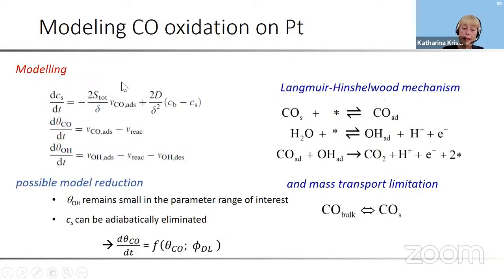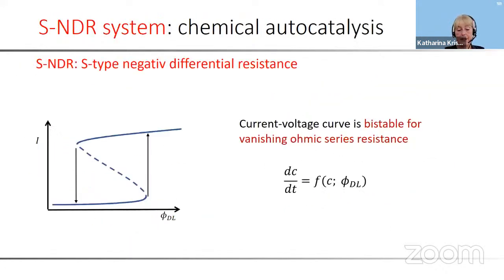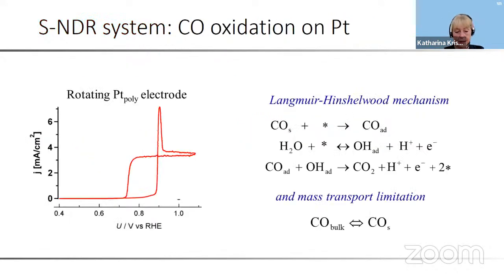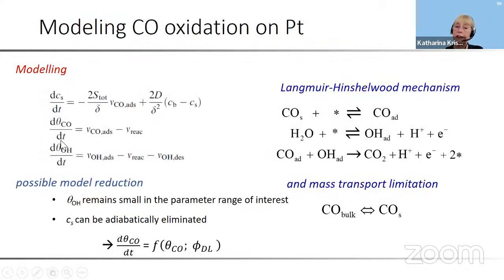If you want to model it, you would end up with these 3 differential equations for the concentration of CO in front of the electrode, for the coverage of the electrode with carbon monoxide, and the coverage of the electrode with OH species. Okay, when I have an S-shaped negative current potential characteristics and a bistable system, as shown here, I have 1 chemical variable. What I want to emphasize here is that in order to form the bistability, you only need 1 true degree of freedom. Your mechanism, as we showed it here, might require 3